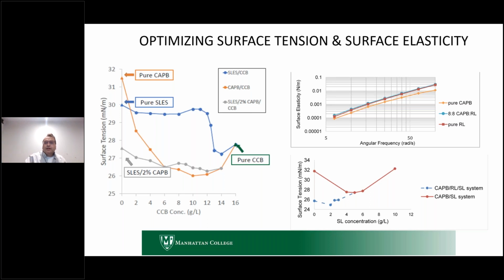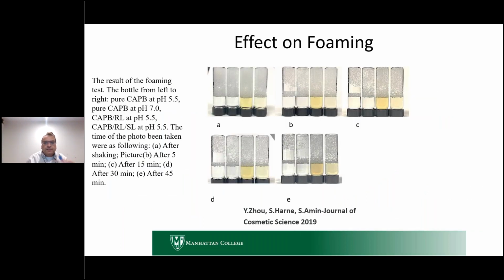I don't go into it here, but this is also in a Journal of Cosmetic Science publication, where we show that we also have a more optimum surface elasticity. So low surface tension, high surface elasticity is a good recipe for good foaming performance, for example, right? So in this optimization exercise, where we're varying all these formulation variables, you can actually start to impact on the foaming performance.